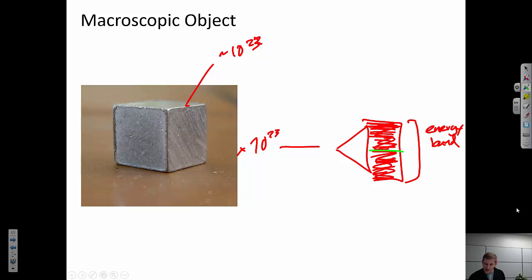So if I looked very, very closely in here, I would see a lot of different potential orbitals, potential energy levels that those electrons could occupy. But the separation between them is very, very small, such that if I'm measuring them with any sort of realistic measurement system that I could think of, there's no way for me to separate out this energy level versus this energy level. And so that's why we think of them as this continuum, this band. So when I'm talking about an energy band, I'm talking about a large number of very closely spaced energy levels.